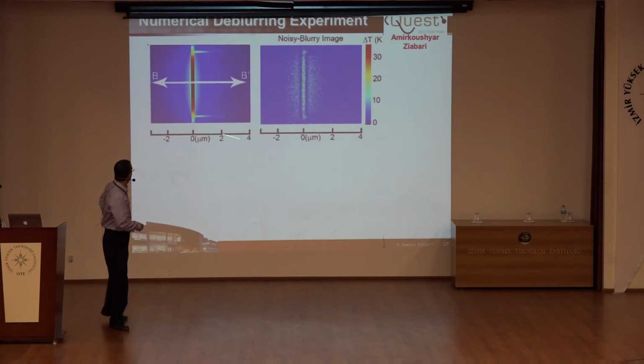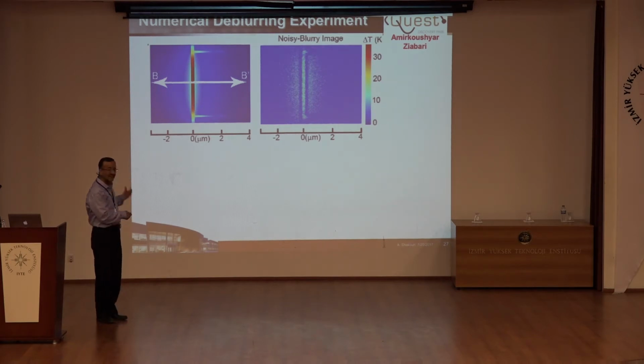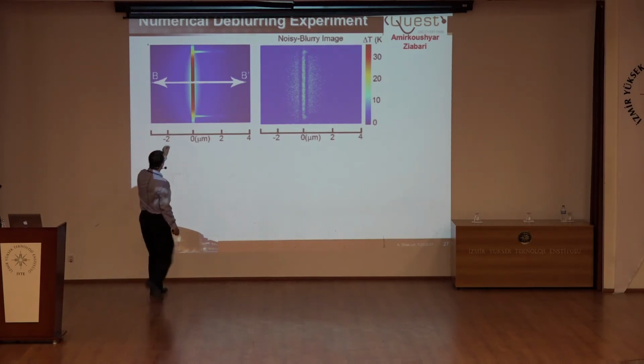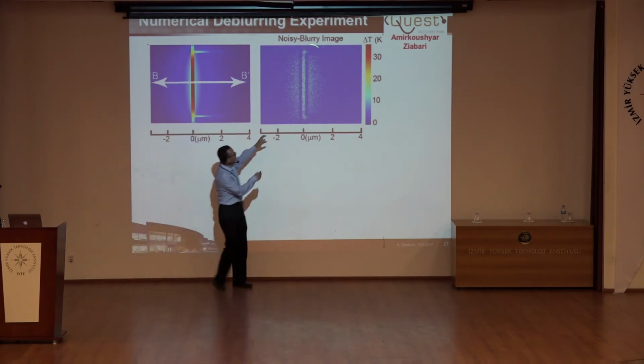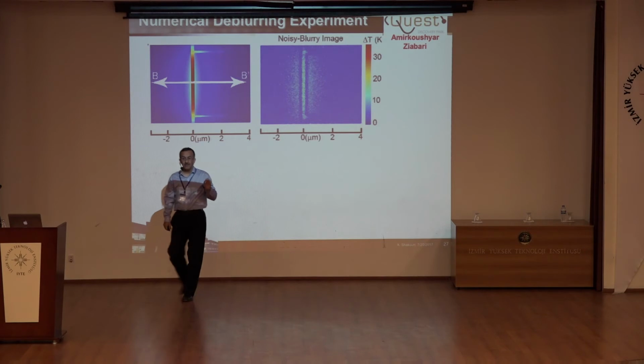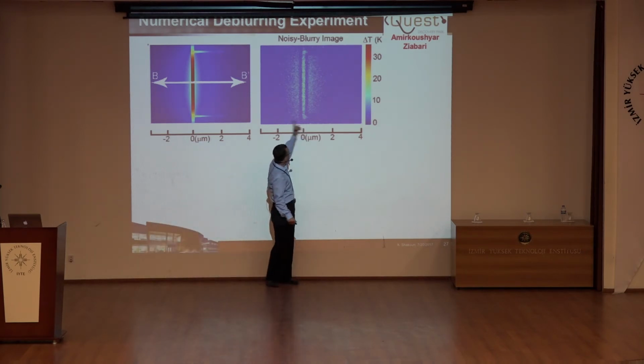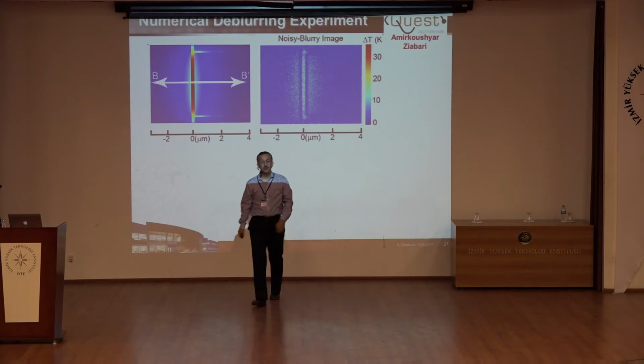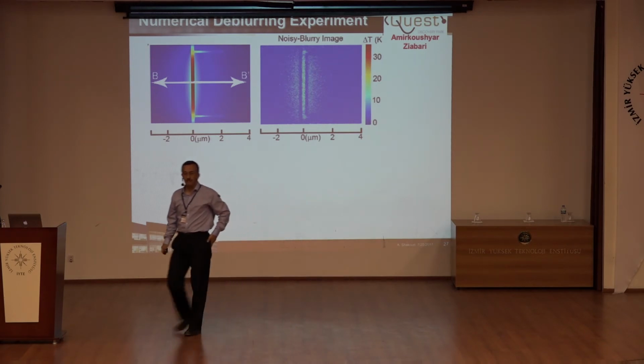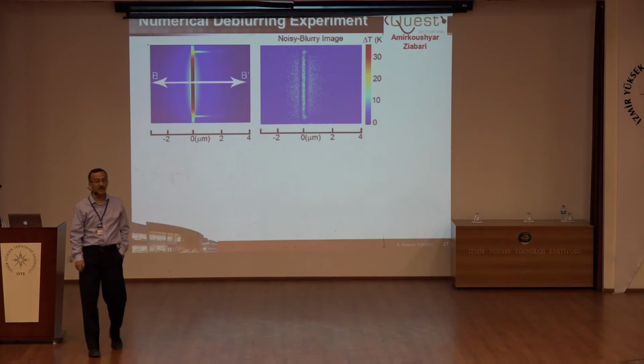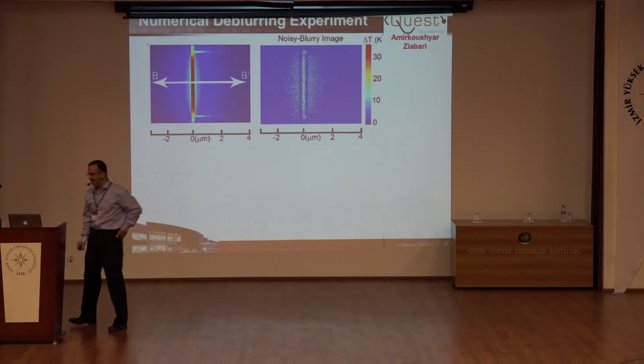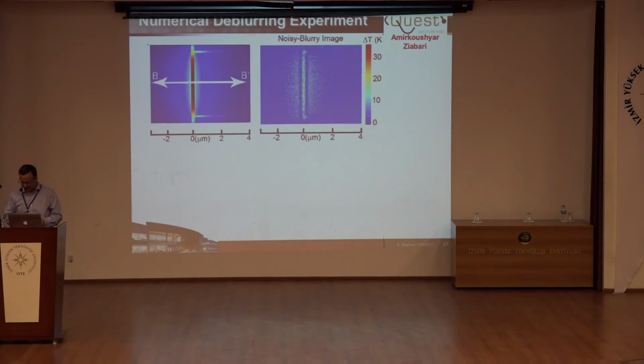What I mean is that if I have an object that is heated, when it's diffracted, every point becomes blurred, and there is some noise. This is what you measure. But at every point, you have information about neighboring points. So if you know the inverse problem methodology from image deconvolution, image sharpening, which is used all the time, you can apply it here. And we have been able with this to go to 100 nanometer spatial resolution. But I will keep it for a little later in case there are questions. Any questions so far?